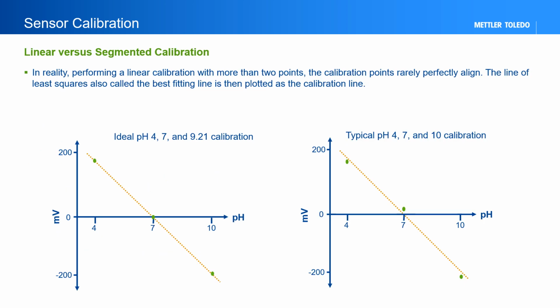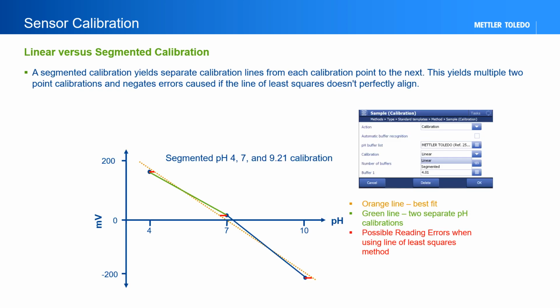Pictured is an ideal linear calibration of a pH electrode using pH buffers 4, 7, and 10. In reality, performing a linear calibration with more than 2 points, calibration points rarely perfectly align. The line of least squares, also called the best fitting line, is then plotted as the calibration line. The segmented calibration in METTLER TOLEDO pH meters and titrators is preferred to avoid the possible errors that could arise from a linear calibration. A segmented calibration yields separate calibration lines from each calibration point to the next. This yields multiple 2-point calibrations and negates any errors caused if the line of least squares doesn't perfectly align with all the calibration points.